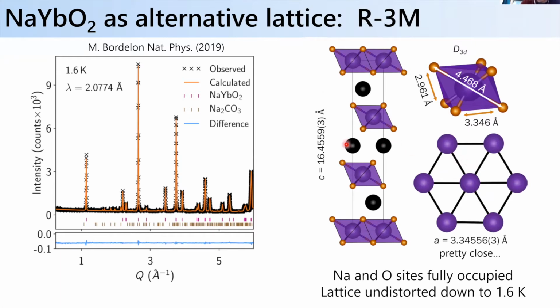However, the sodium planes that space them basically lack a comparable level of alloy disorder, right? And so we can do neutron diffraction on this system, and we can show that the sodium sites are fully occupied within the planes, as well as the oxygen sites. This is sort of counterintuitive for people who've worked with a lot of sodium materials, because oftentimes you have sodium vacancies, but the ytterbium really loves to be 3+, and ytterbium oxide is very stable. So this system is a reasonably stable system. It doesn't really want to give up its sodium. Okay, it's not a good cathode system, for instance.